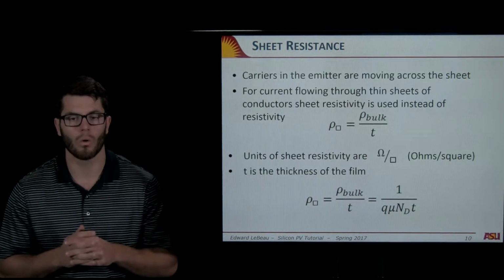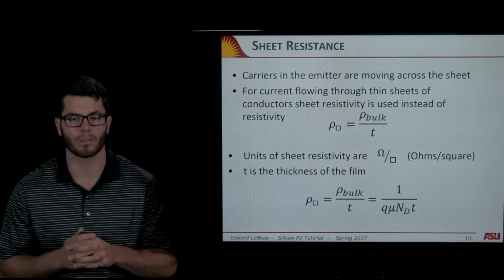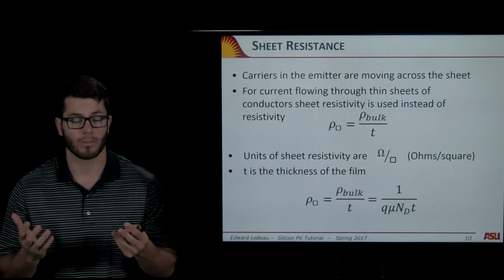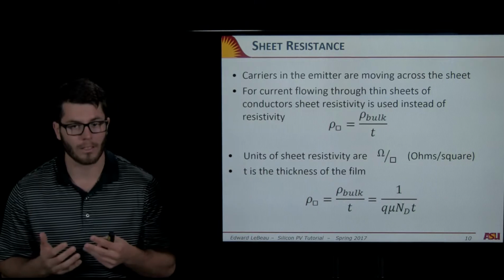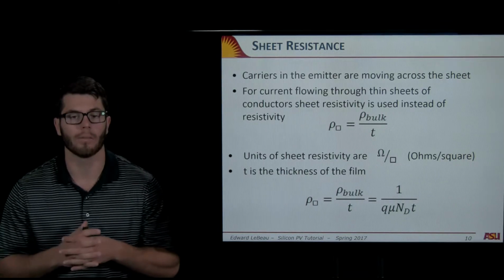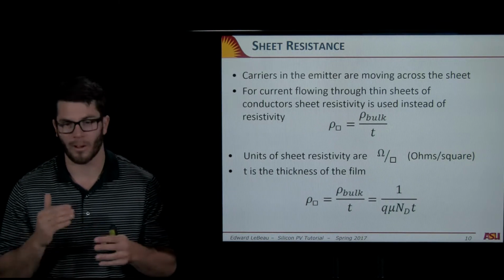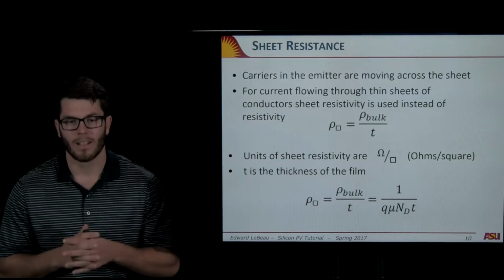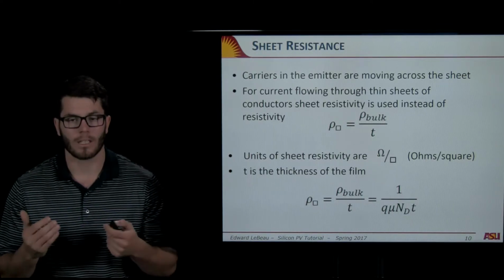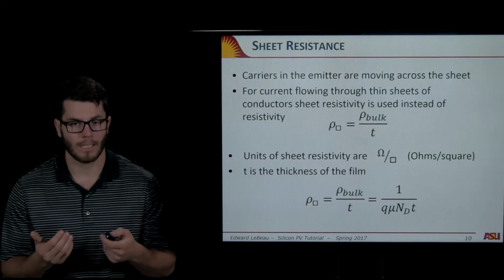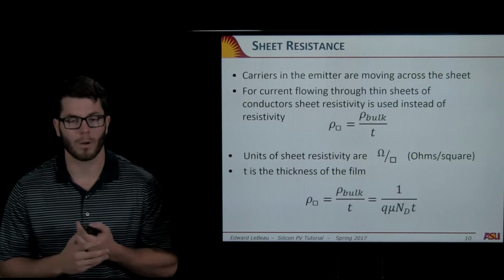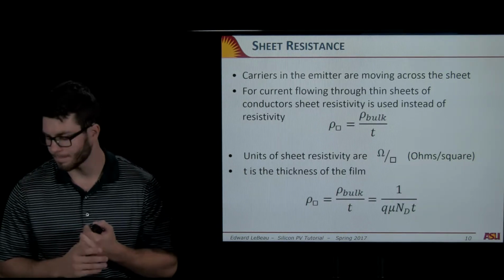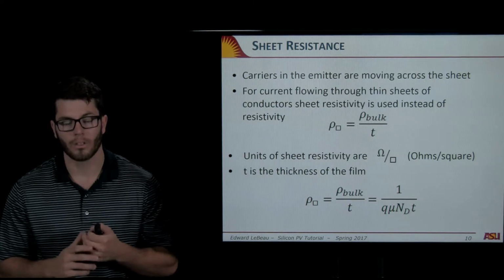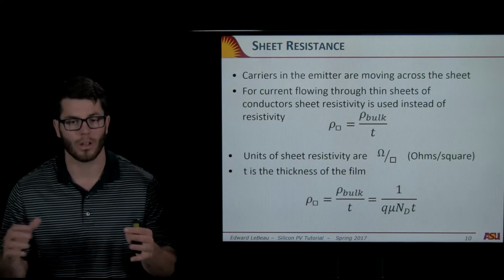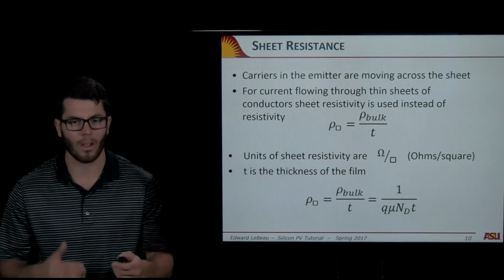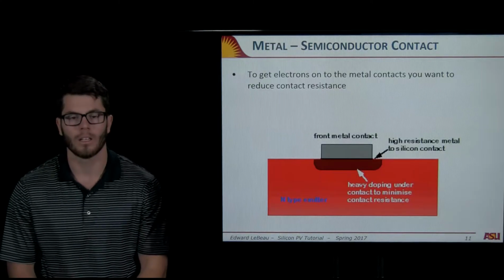So you want a low sheet resistance. If you increase your doping density, your sheet resistance goes down. But remember that has negative effects with your recombination. So remember, we're at this delicate balance again. And also remember, there's your thickness. You don't want t, your thickness, to be too thin, or as we spoke about earlier with your absorption coefficient, you're not going to absorb things in your solar cell if you're too thin. So there's all this delicate balance going on.